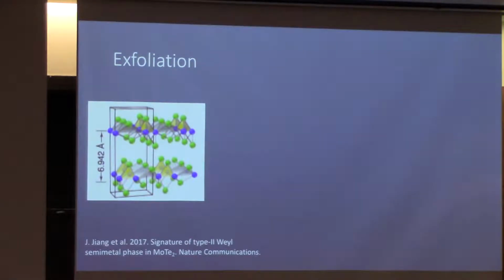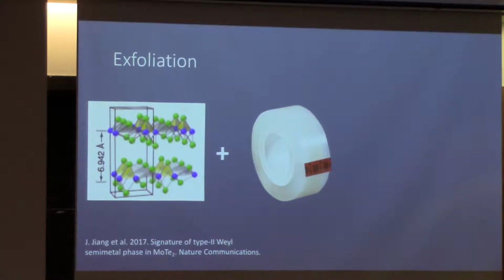So MoTe2, which is the structure you can see up on the left there, is a van der Waals bonded crystal. So you can imagine it as like a stack of sheets of paper. The bonds within each layer are strong, but the bonds between the layers are rather weak. So weak, in fact, that I can take an ordinary piece of tape, peel off a few layers of crystal, and slap them down on a substrate to make a flake like this, which can be as thin as, so far, we've gotten it down to 20 or 30 nanometers.